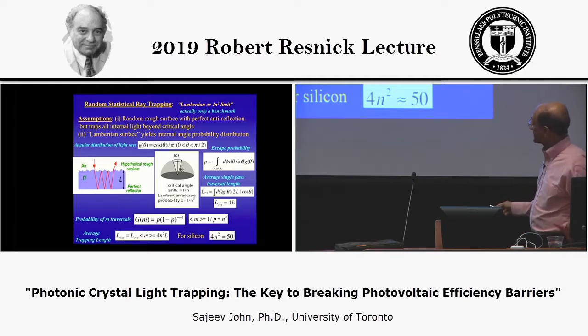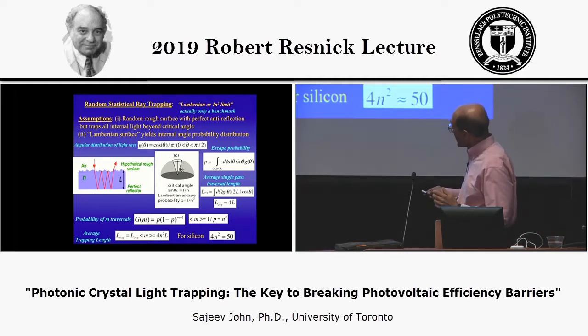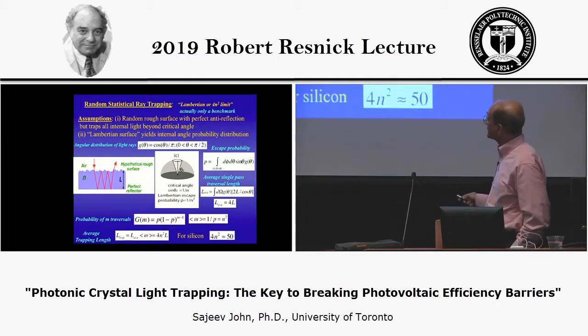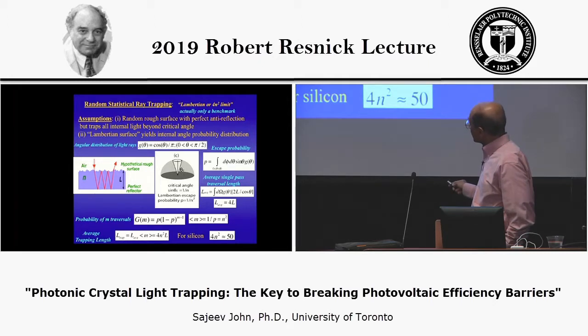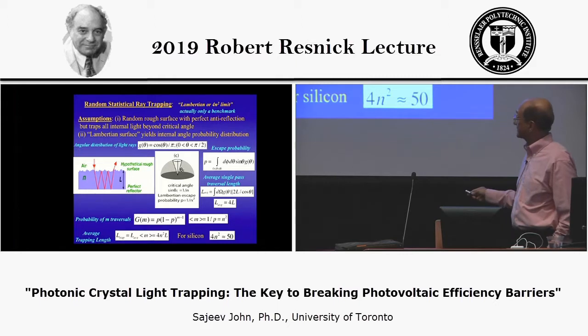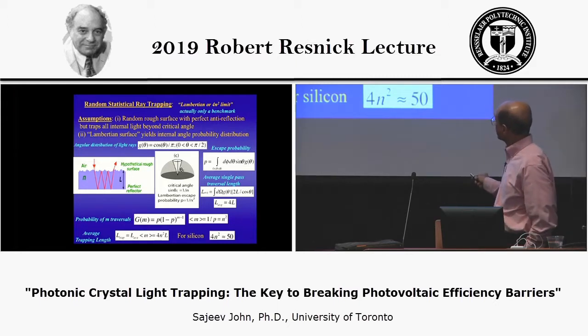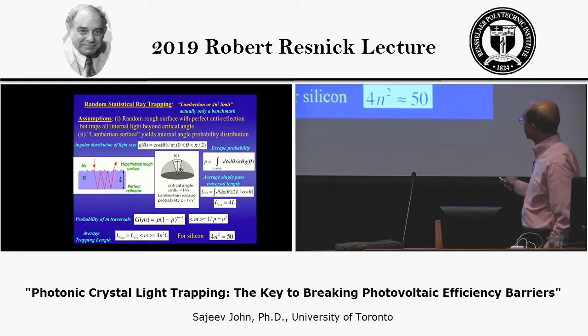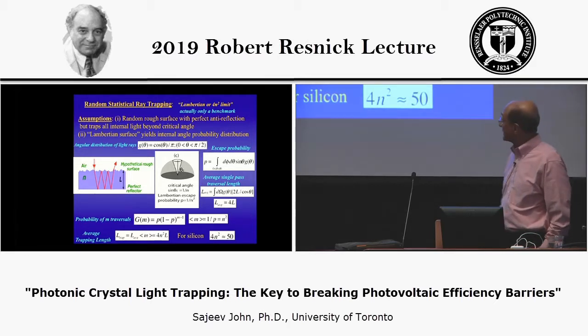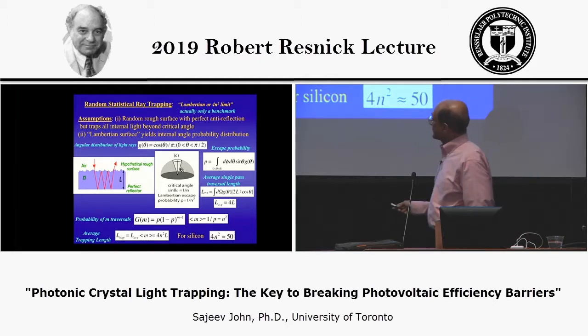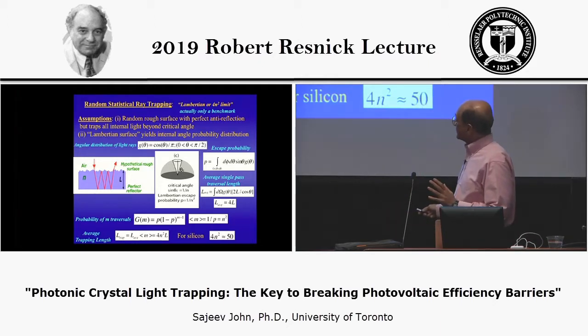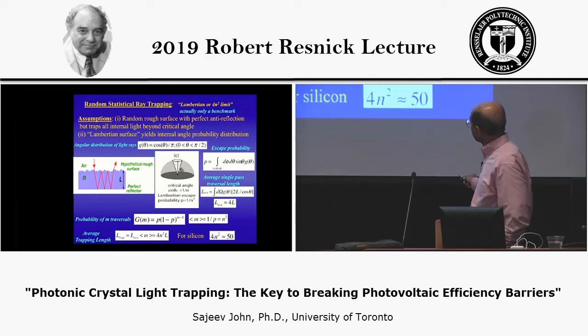And then we'd like to have many bounces, not just one. You could ask, what is the probability that it'll make an integer number m of bounces before it finally escapes? In order to do that, on the first m minus 1 attempts, it should not escape, with probability 1 minus p. And on the final mth attempt, it does escape, with probability p. So this defines a distribution function for the number of bounces. And you can calculate the average number of bounces with respect to this distribution. It turns out to be just 1 divided by p, or in this case, n squared. So by this statistical trapping argument, the average trapping length would be given by the average path length on a single bounce multiplied by this average number of bounces.